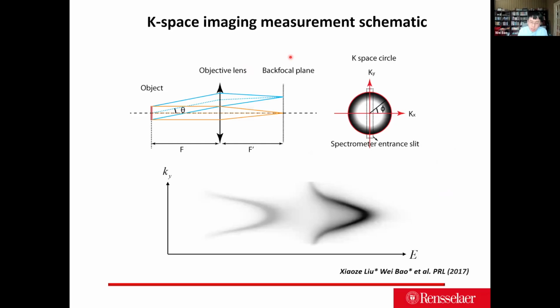And experimentally, observing this strong coupling optically in the exciton-polariton community is also very easy. Suppose we have a microcavity sample. We try to see the emission angle from this cavity, and because of K space, the same emission angle will form a spot in the back focal plane. So with the same angle, you easily project it into a K-space circle, and at the spectrometer entrance, you just select this slit and disperse. So K is selected by the spectrometer entrance, and E is selected by the spectrometer dispersion over the different wavelengths. In this way, by simple K-space imaging, back focal plane imaging, with the spectrometer, you can easily see the E-K diagram of the exciton-polariton system optically without complicated measurement.